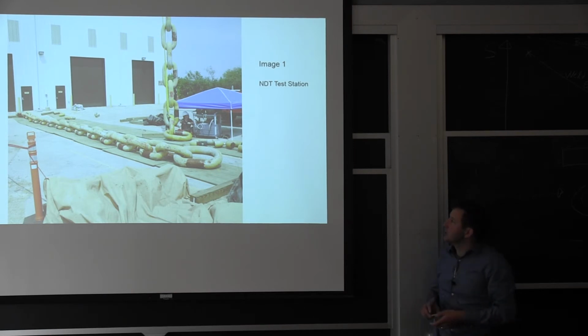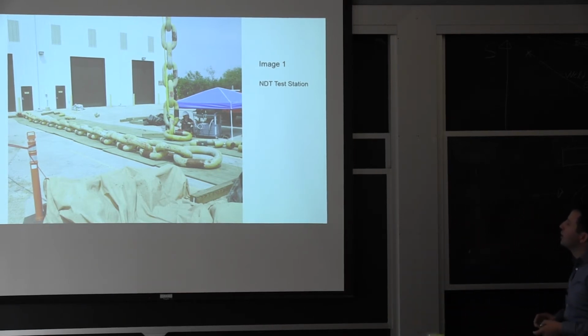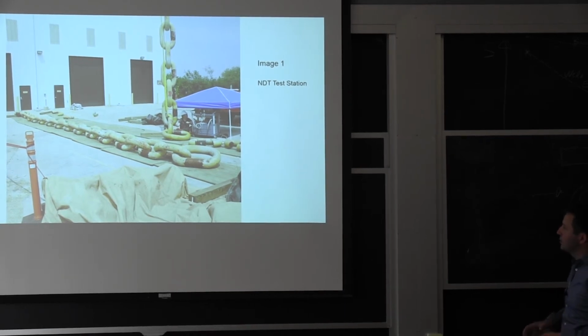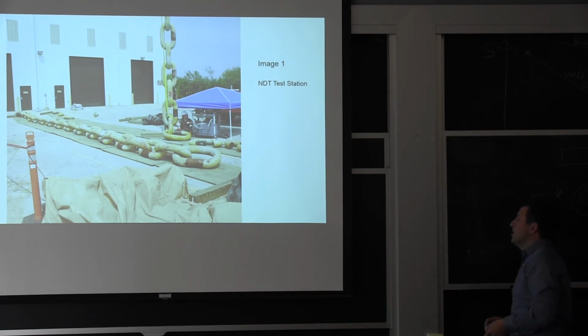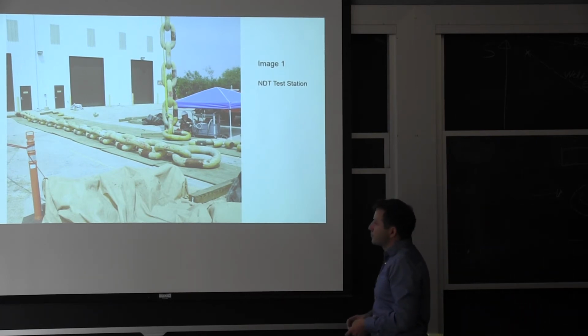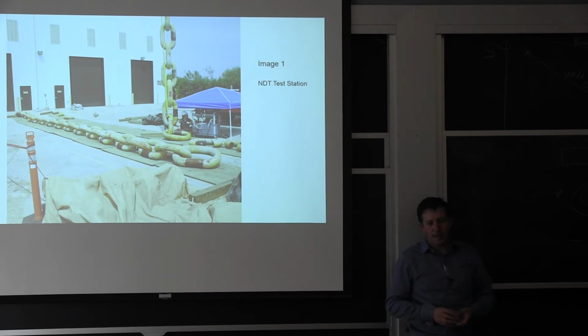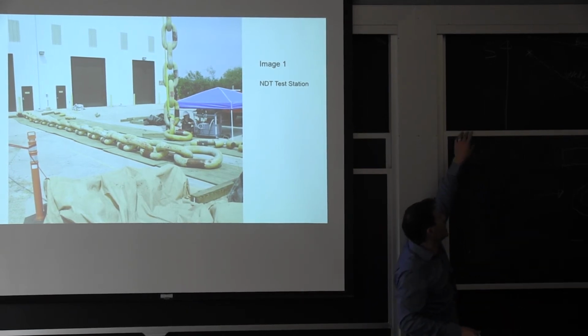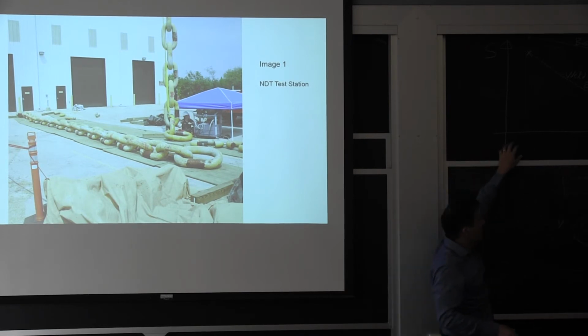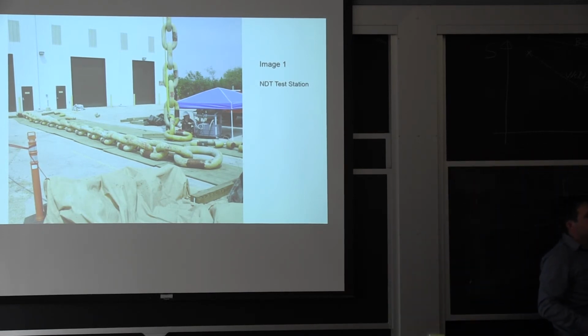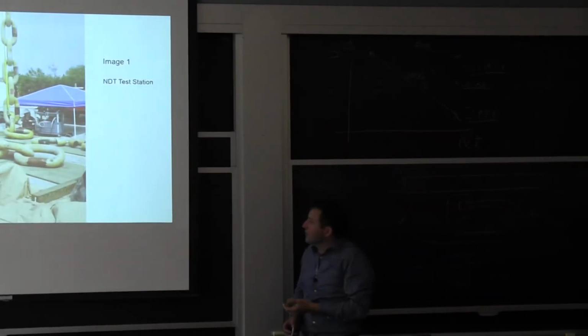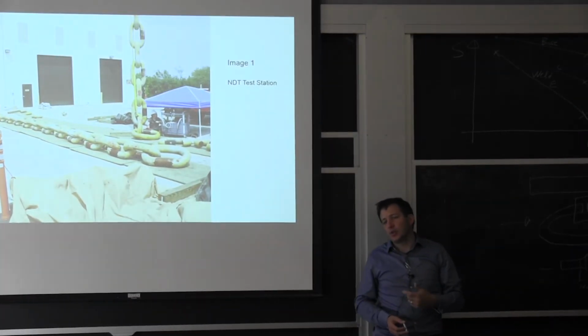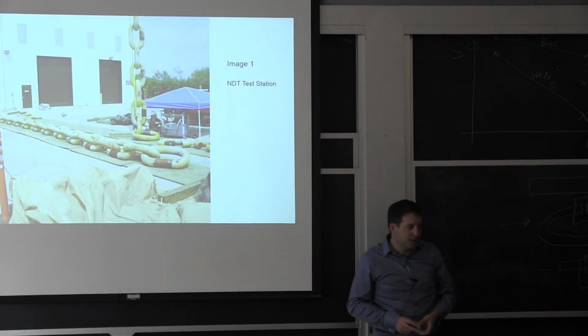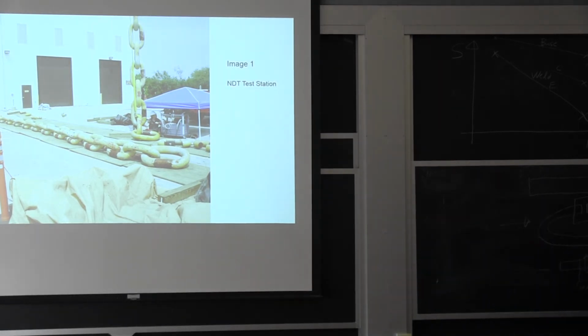Now, these chains were essentially a federal investigation where they were holding a production riser for oil and gas offshore, very deep, and there really wasn't any cyclic load in the sense of what we were looking at here, but it was a time effect, going over time because the hardness was really high in the heat affected zone. They ended up with cracking that normally wouldn't take place. Now, there was a very specific reason why they ended up with these cracks.